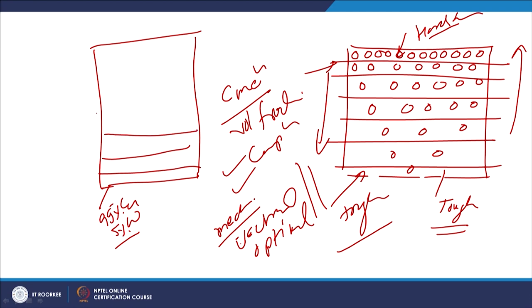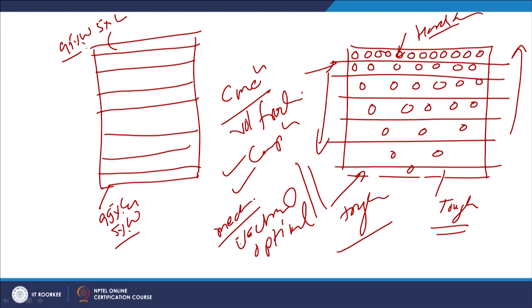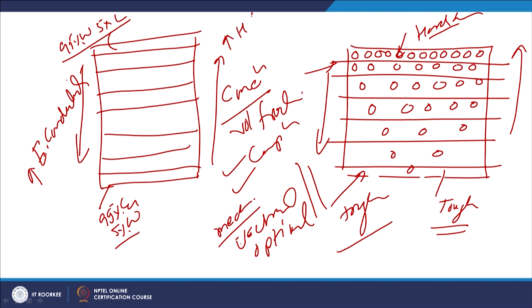And on the other hand, increasing tungsten concentration and reducing copper percentage, at the top we may have 95% tungsten and 5% copper. Such materials will offer increasing electrical conductivity in this direction, while in the opposite direction they will offer increasing hardness and increasing refractoriness. So, such gradients are possible through controlled variation in composition or constituents, so that the required combination of properties is achieved.